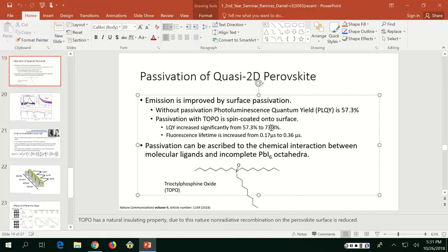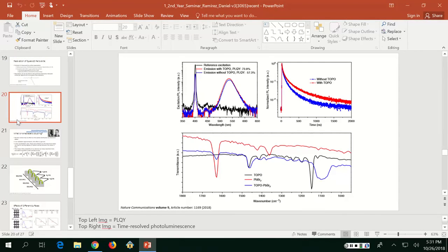I don't know if it is that trend, and I know Aaron knows perovskites pretty well. I don't know if the longer lifetime necessarily means in all materials it would have a higher PL. That's why I said it's a general trend. If you just assume it's radiative and non-radiative recombination, if you just assume those 2 pathways, then you generally expect that the longer your experimentally measured lifetime curve is, the higher your quantum yield.